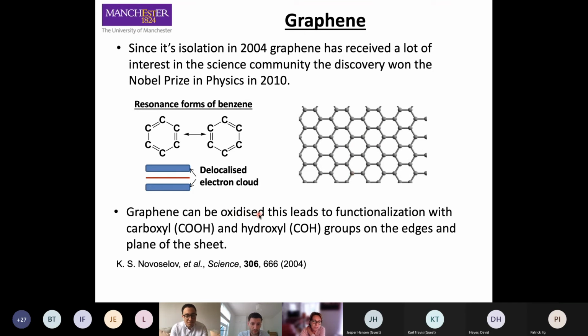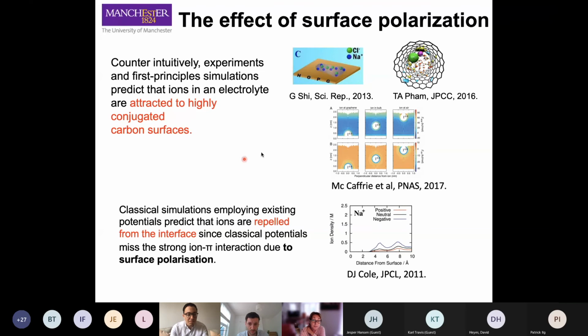However, if you use very potent oxidizing elements, you can actually oxidize both the surface, usually with hydroxylic groups, and also the edges where you have the hydrogens that are more reactive, and these usually are replaced with carboxylic groups. When you do this, you obtain what is called graphene oxide. We have been working a bit on graphene oxide, but in this talk I'm going to focus only on graphene, so a completely unfunctionalized surface.